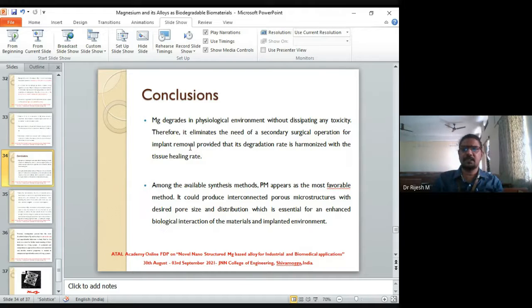Among the available synthesis methods, we found that powder metallurgy appears to be the most favorable method. The reason for this is you can actually control the interconnected porous structures with desired pore size and distribution. It is essential for an enhanced biological interaction of the material and the implanted environment.